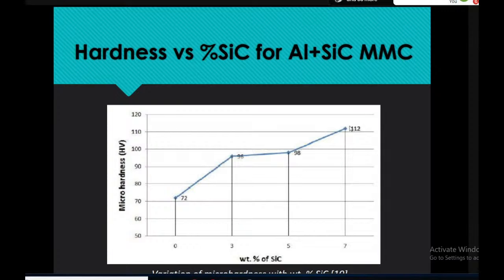It is not the case that if you add 20% SiC you get the same performance. No, that is not possible. If you add more than 10%, this could drop and the material completely becomes brittle. So we cannot do that. This is again a trial and error that you should have, and then you can have better performance. So 112 is the Vickers hardness we can receive at 7% weight percentage of SiC.